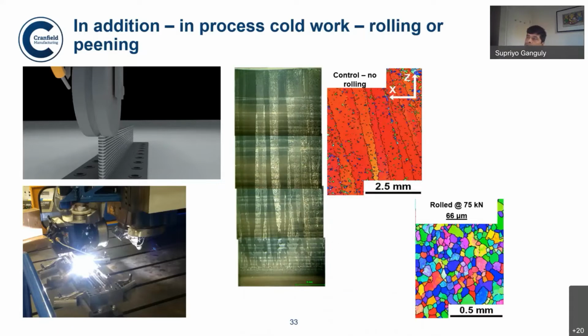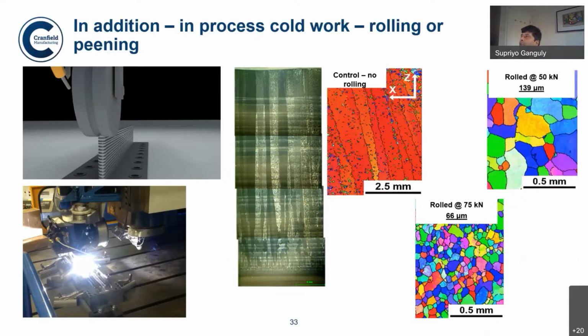In this particular wall, if you can see my mouse, it is showing the large epitaxial growth of the grains, and the EBSD image is shown in red on the right hand side. And then when we roll it, and we can vary the rolling load, with 50 kilonewton, this is showing the prior beta grain size which was generated at high temperature, which then resulted in the alpha grains. As you can see, the prior beta grain size when rolled with 50 and with 75 shows a significant reduction. So it is possible to control the grain structure of such deposit through application of cold working.